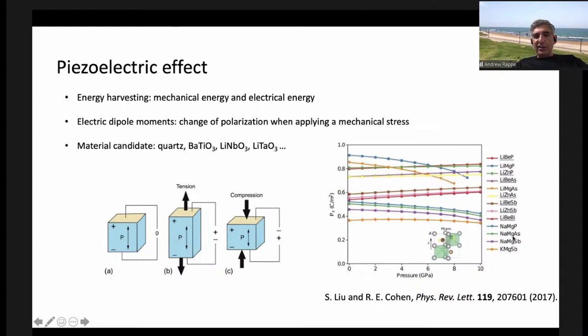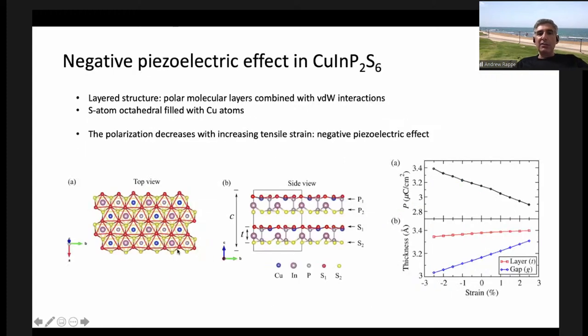However, these authors have made this beautiful graph here, which shows that under pressure, when you're compressing the material, for some of them the polarization gets bigger. You see, there are several lines with positive slopes here. So those would be negative piezoelectrics. And that's kind of surprising that that could happen that way. And so we thought we would look at one of them that has some interesting chemical bonding properties from other points of view, and I'll tell you about that now.